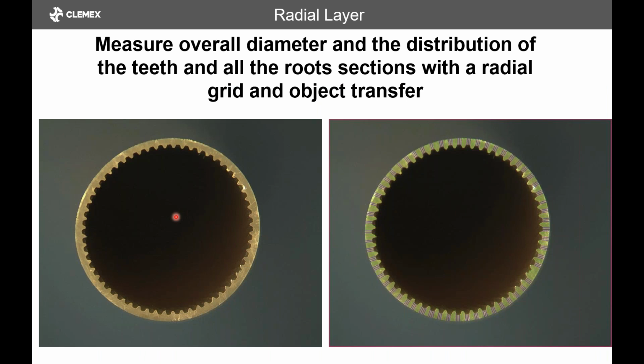Now here it's not really a coating, but in this case it would behave on the same principle, in the sense that the intent was to measure the valley's thickness versus the spike thickness, the teeth rather. And so the idea was to use a tool that we call a radial grid. So basically it makes like a star, if you want. And then you pick up all the lines, and then you separate the lines that are part of the valleys versus the lines that are part of the tooth. And then you can get a distribution value for both of them.